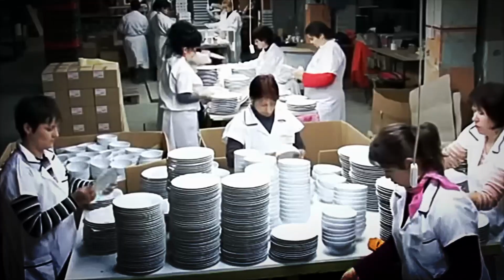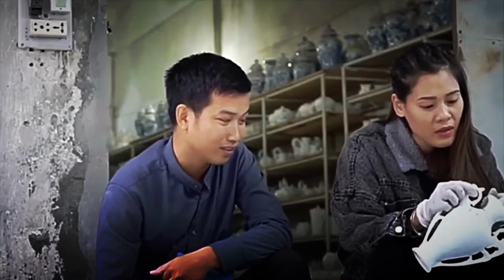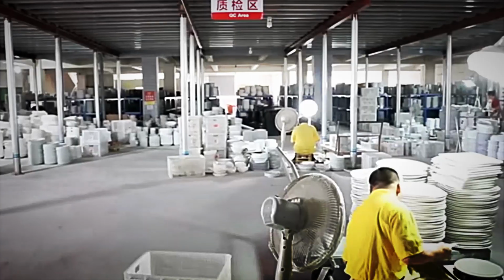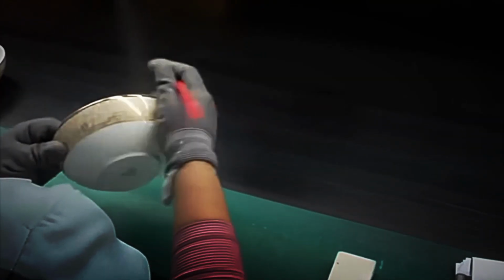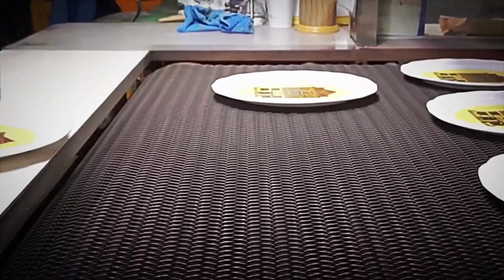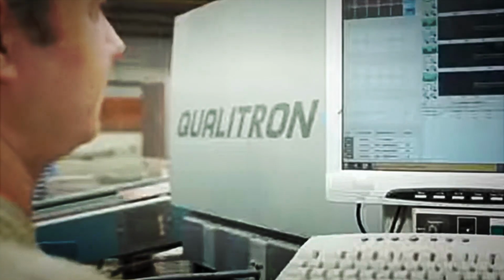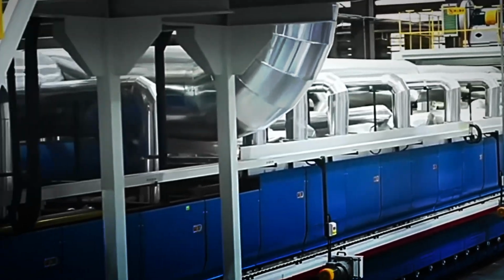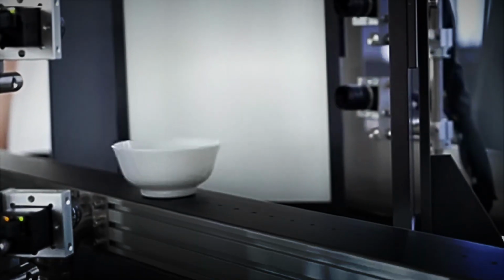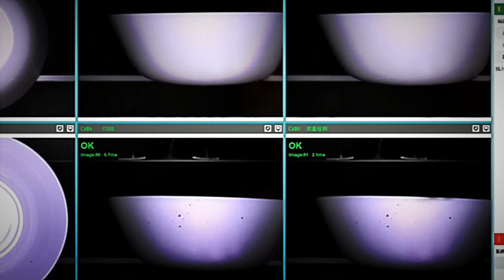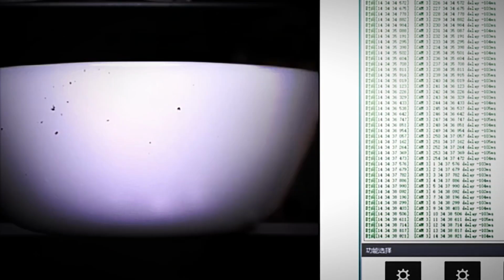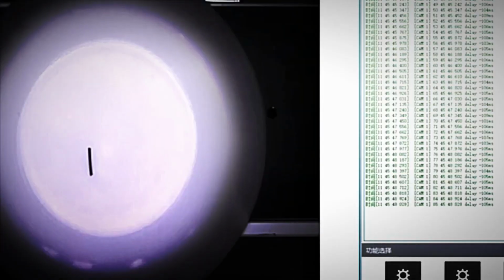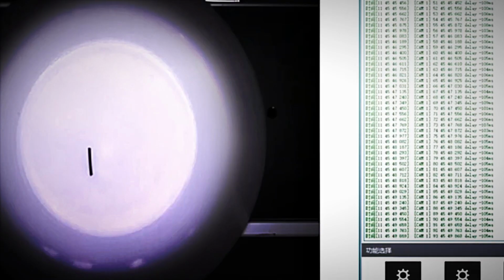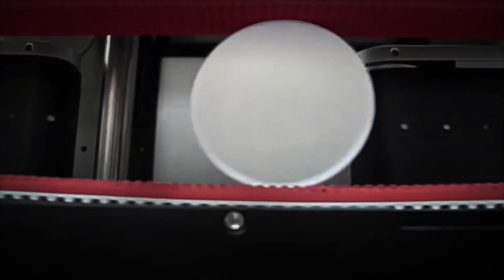Here, under intense lights, technicians examine each piece for imperfections, tiny pores, glaze drips, misaligned patterns, or minimal deformations. Many factories employ combined ultrasound and laser systems. Ultrasonic waves pass through the ceramic walls and return to the sensor, allowing the thickness to be measured with impressive precision. Simultaneously, lasers generate a three-dimensional model that is compared to the ideal shape programmed into the system. If a piece shows deviations, even small ones, a robotic arm automatically removes it for reprocessing or disposal.